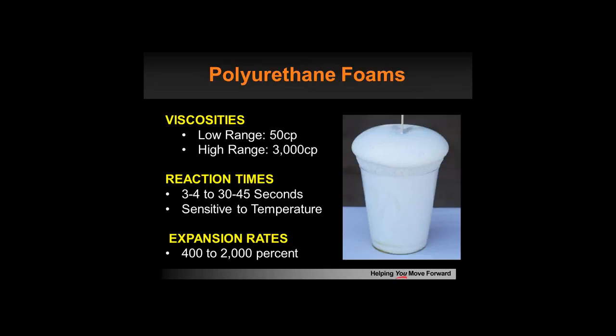Typical of the urethane foams, they have a wide range of viscosities, as low as 50 centipoise to as high as 3,000 centipoise. Reaction times can vary from a few seconds upwards to 30 to 45 seconds and sometimes a couple of minutes. And they can be sensitive to temperature. They have a wide range of varying expansion rates depending on the product you might use, as low as 400 to as high as 2,000%.